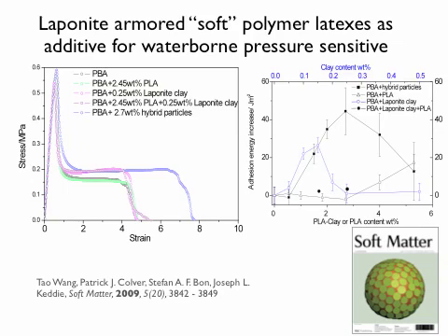So the black dots and the black line in the left figure is a polybutyl acrylate sticker material. So you look it up, and you see initially you get a lift off, and then it comes down, and you see a plateau forming here, and that's where you get fibers. So you remove this adhesive, you get these fibers, and when the fiber breaks, you have no interaction anymore, it drops to 0.